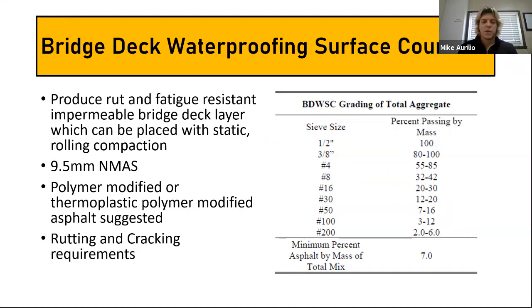Bridge deck waterproofing surface course. New Jersey has old infrastructure, and they were interested in developing a mix that would be compactable on a bridge surface with static rolling compaction. They can't use a vibratory compactor because of the age of some of their bridges. So they produced this mix. It's a 9.5 millimeter nominal maximum aggregate size, 7% AC content. They suggest that it's polymer modified or modified with a thermoplastic. Usually polymer modified refers specifically to SBS, which is what we use primarily in Ontario. And this mix specifically had a rutting and a cracking requirement.